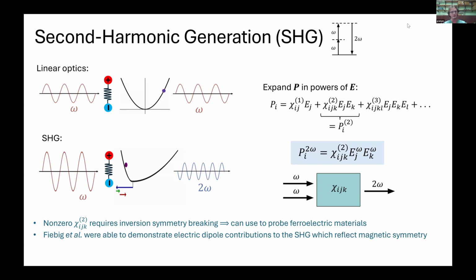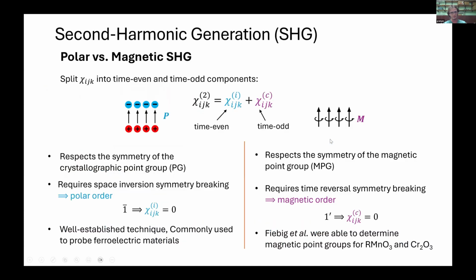This is not that. This is a bit more curious because this time odd component actually comes from the Ginzburg-Landau functional theory of phase transitions formalism. And the reason this component is time odd is because it's a product of a 6-rank axial time even tensor and the antiferromagnetic order parameter, which is time odd and axial. So this gives you a time odd polar 3rd-rank tensor. And if you really want to go in and figure out where you can find optical effects where you will have magnetic symmetry, I think that is the way you would do it. I don't understand it super well, though.